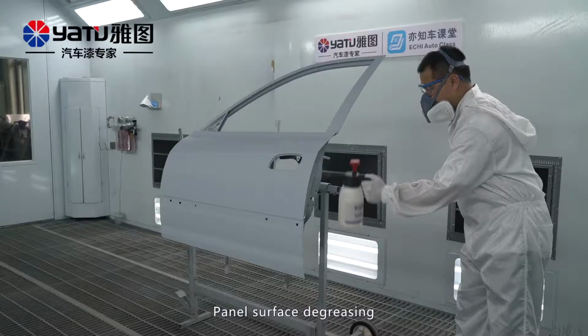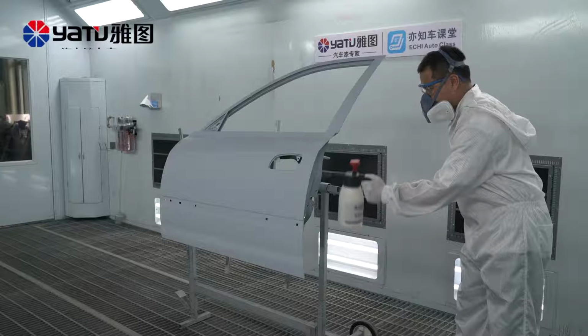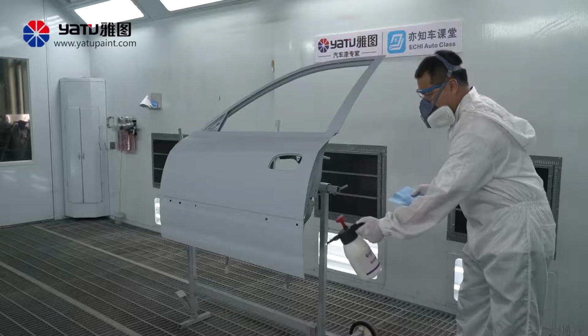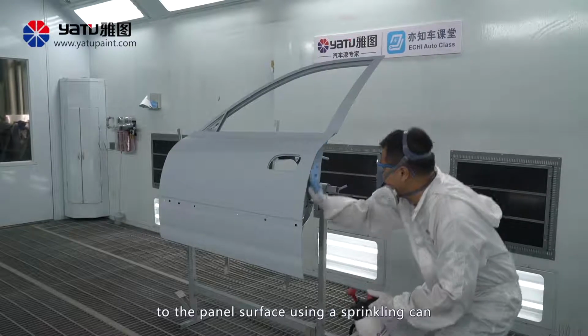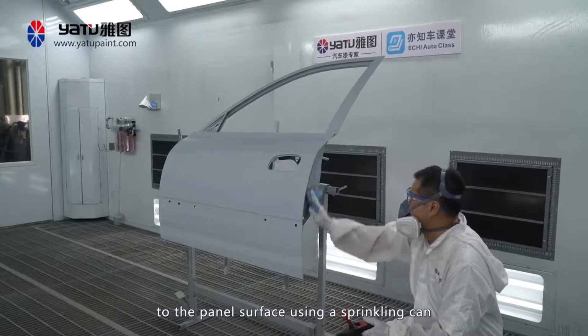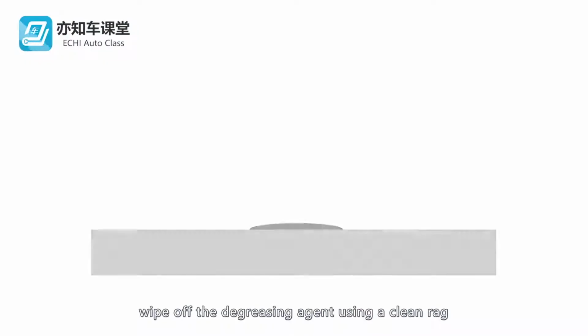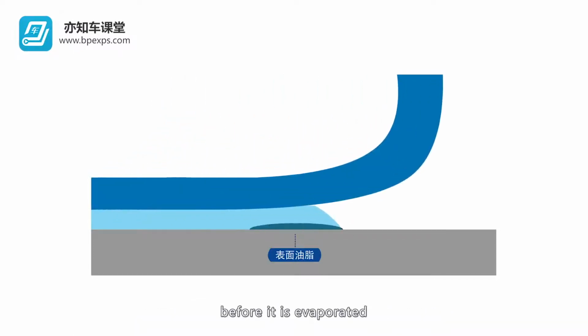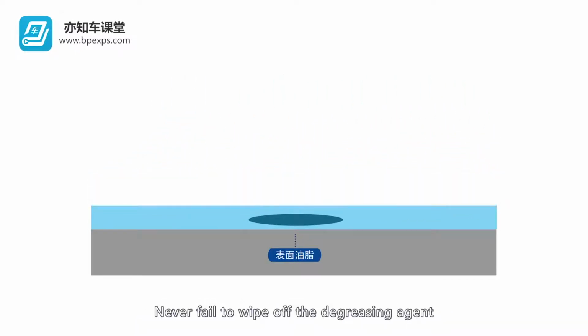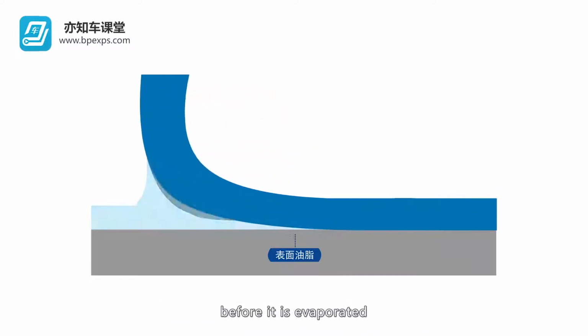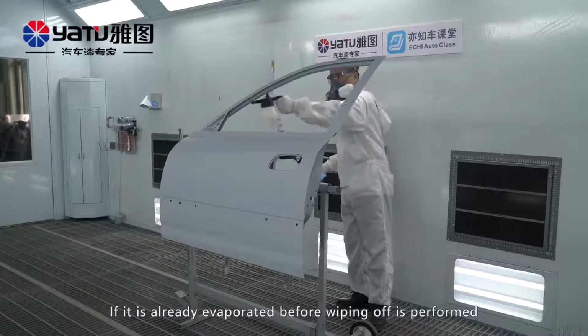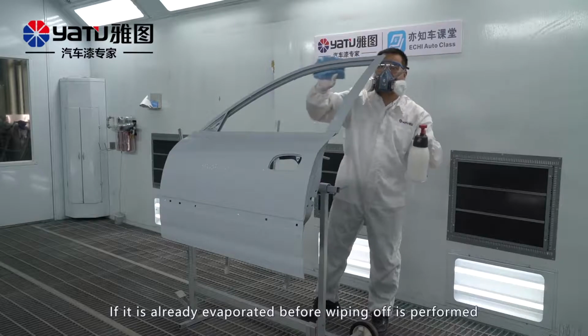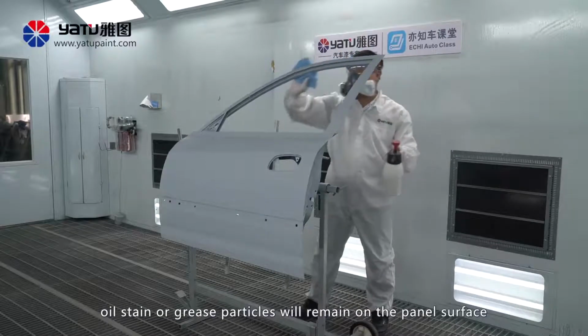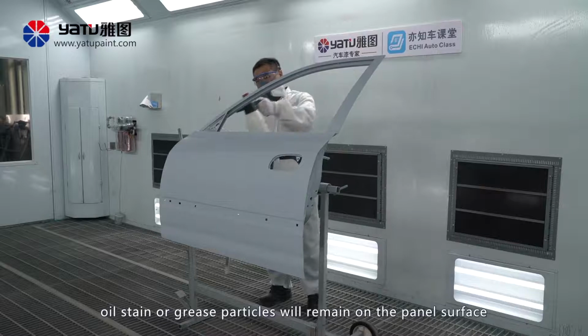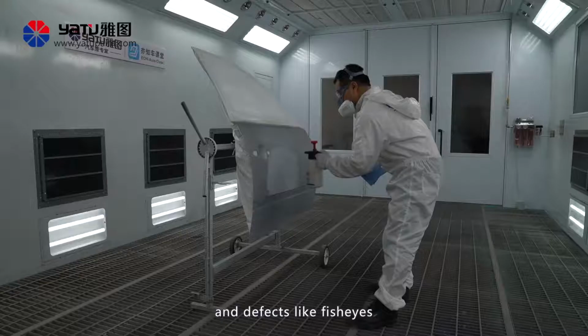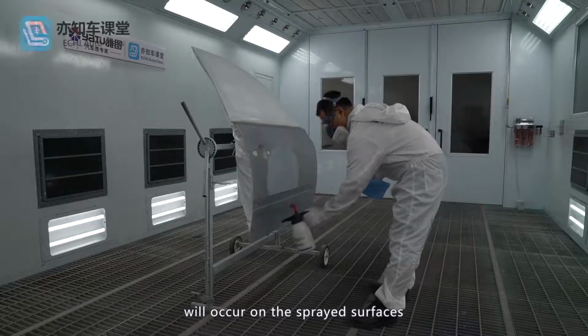Panel surface degreasing. First, spray degreasing agent to the panel surface using a sprinkling can. Wipe off the degreasing agent using a clean rag before it is evaporated. Never fail to wipe off the degreasing agent before it is evaporated. If it is already evaporated before wiping off is performed, oil stain or grease particles will remain on the panel surface, and defects, like fisheyes, will occur on the sprayed surfaces.